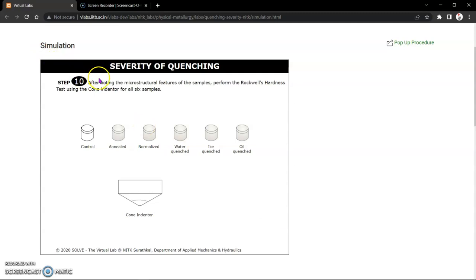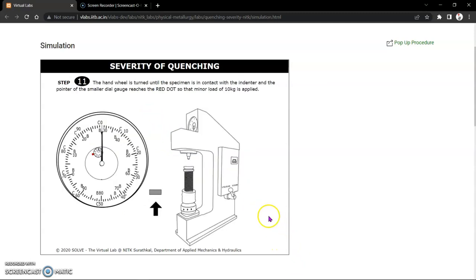Step 10. After noting the microstructural features of the sample, perform the Rockwell hardness test using the cone indenter for all 6 samples. At step 11, the hand wheel is turned until the specimen is in contact with the indenter and the pointer of the smaller dial gauge reaches the red dot, so that a minor load of 10 kg is applied. Then we adjust the specimen height.